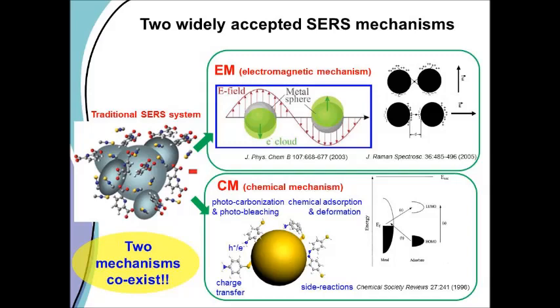There are two mechanisms. There's the electromagnetic one that's been studied for a long time, which has to do with the high dipole, well, it's not dipole, multipole effects that you can get if you have an irregular particle. You get all kinds of field components, derivatives of the field. And that's what the electromagnetic effect is about for SERS. But very few people have looked at the chemical mechanism. It turns out that in graphene, you get a good chance to look at the chemical mechanism, and that's what I'm going to talk about for the rest of the time today.